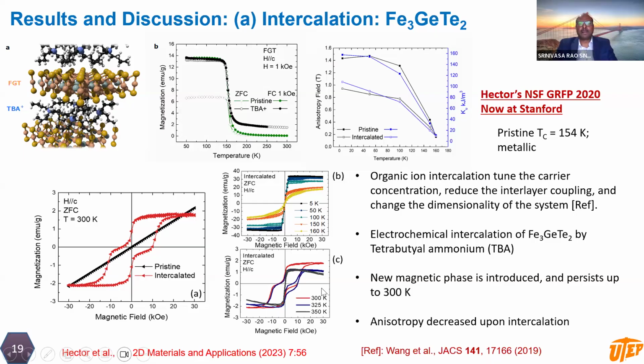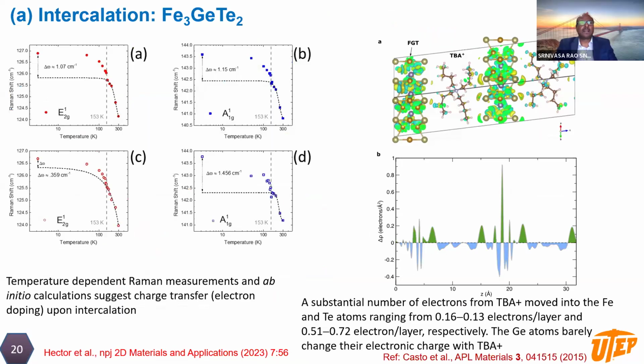Okay, and we have done temperature dependent isothermal measurements, and as you can see, until 300 K, this compound showed hysteretic behavior. So that shows that upon intercalation, this compound enhanced its ferromagnetic phase from 150 Kelvin to almost 300 Kelvin. To better understand this, we expanded these measurements as a function of temperature and magnetic field using Raman spectroscopy. Our collaborator Satnish conducted these measurements, and we computed how the Raman shift is changing as a function of temperature.